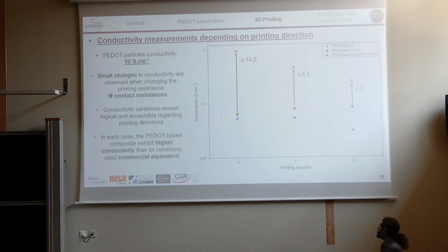And so, for example, in the X direction, which is the one that we are interested in the most, because it's just one continuous line, we are more than 10 times more conductive, which means that for the same circuit, you will need to use 10 times less material. So that's a good advantage.